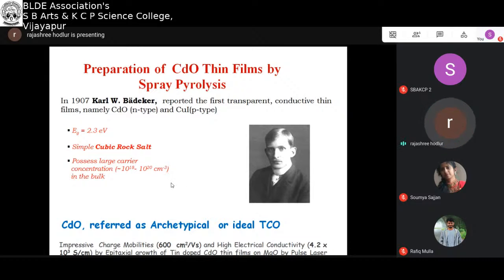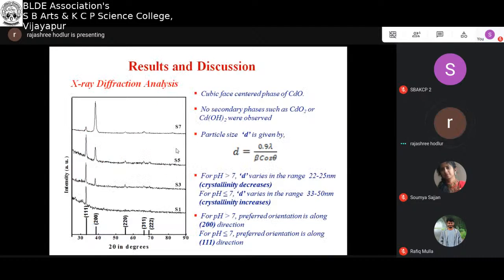And this cadmium oxide is referred to as an archetypical or an ideal TCO because it exhibits impressive charge mobility of around 600 centimeters square per volt second and a very high electrical conductivity. So, in our laboratory, we were able to make thin films of cadmium oxide using the home-built spray pyrolysis technique, and various characterization techniques were used to confirm their crystallinity.